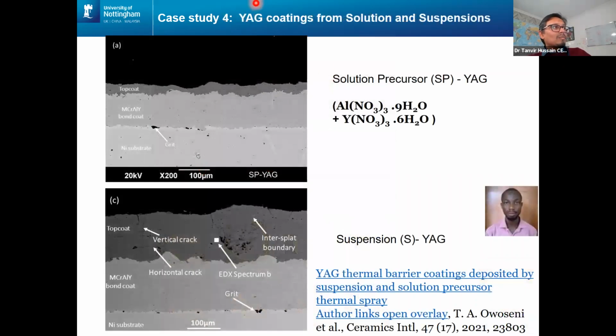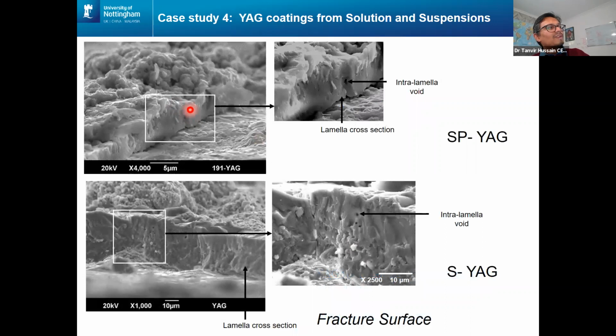Similarly, we're working with yttrium aluminium garnet, because YAG is another material which has high temperature capability and doesn't go through a phase change at the operating condition. To make that YAG layer, we were using aluminum nitrate and yttrium nitrate salts. Tunji, who has already finished his PhD, and I were comparing how a solution precursor YAG compares to a suspension YAG. Here are some fracture surfaces of these lamellae, or splats. You can see the splat microstructure from a suspension sprayed coating is quite different from a solution precursor sprayed coating, because the mechanisms they go through and the degree of porosity that they develop are quite different as well.